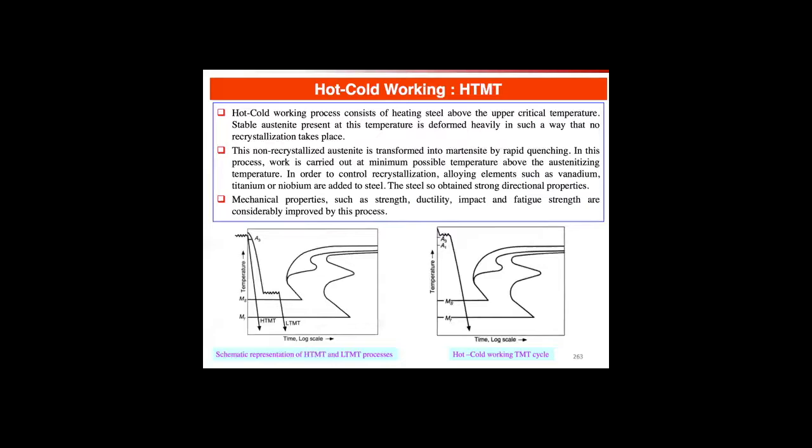And it's all about the direction and the same microalloying elements, vanadium, titanium, and niobium, right, that were really important for pinning the grain boundaries before. If we add enough of them, they also slow recrystallization, right? So getting the balance between a steel that does well by controlled rolling versus a steel that is good under HTMT is really the balance of those microalloying elements.